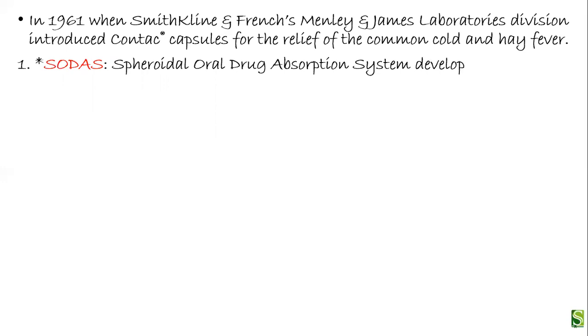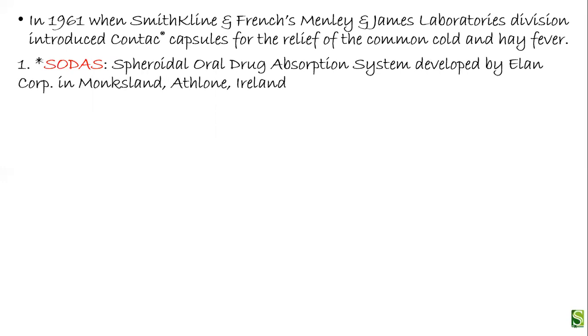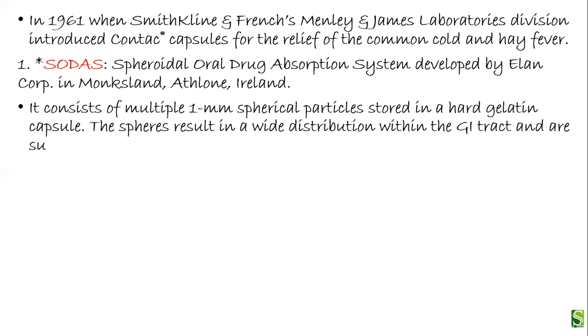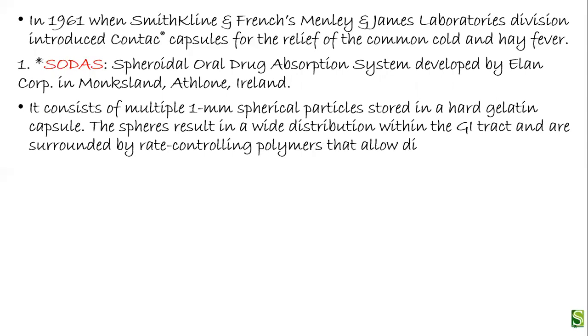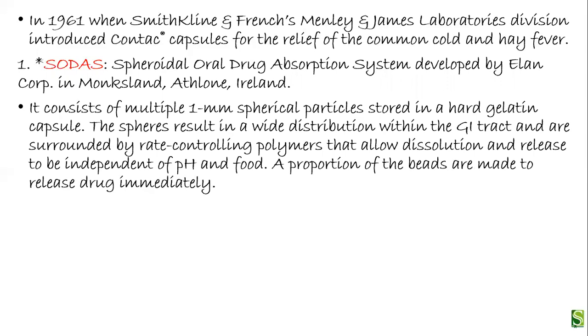In 1961, Smith Kline and French introduced Contac capsules, a registered trademark, which were prepared for relief of common cold and hay fever. Next was SODAS, which stands for Spheroidal Oral Drug Absorption System, developed by Elan Corporation in Athlone, Ireland. It consists of multiple 1 mm spherical particles stored in a hard gelatin capsule. The spheres result in a wide distribution within the GI tract and are surrounded by rate-controlling polymers that allow dissolution and release to be independent of pH and food. A proportion of the beads are made to release the drug immediately, and half are made to sustain the drug release, controlled by varying the thickness of the polymeric membrane.